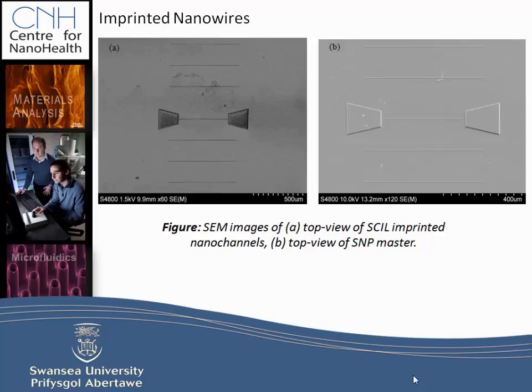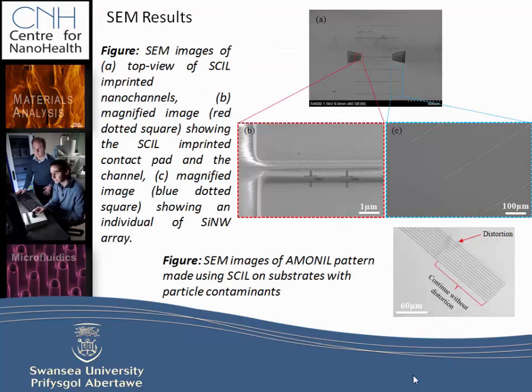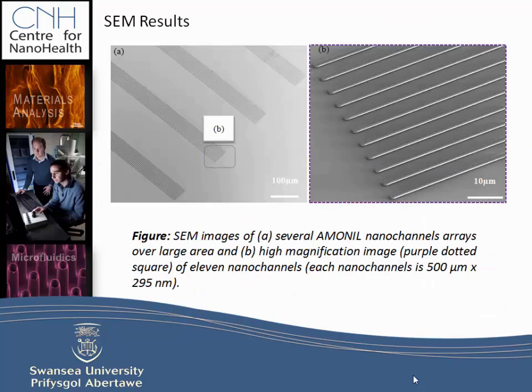This is just fabrication of the stamp master, and the crucial point here is that the replicated nanowire is the same as the nanowire on the initial master. Okay, and indeed you get very, very good replication. So the quality of the nanowire depends really on the initial master stamp quality. Okay, so you can see very nice, neat nanowires, arrays of them, and these are produced over a 4-inch wafer. So this would take you many, many hours to write a pattern like that using an electron beam tool. Okay, this replication process takes only about 10 minutes.